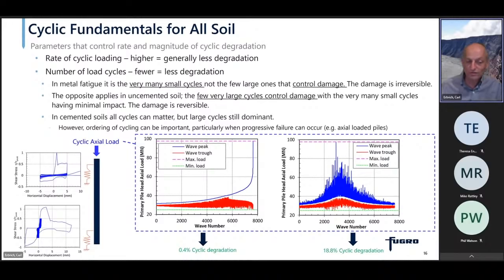In cemented soils, it's a bit different. All soil cycles can matter. The large cycles are still the dominant feature, but the ordering of cycling can be important, particularly when progressive failure can occur, e.g. as in axially loaded piles, which is the example I've got here. On the left here, we're showing an axially loaded pile with a couple of t-z curves. These are based on actual lab CNS tests. So you can see in both cases, when we push them to failure, we're getting very brittle results. In fact, this is the one I showed earlier.